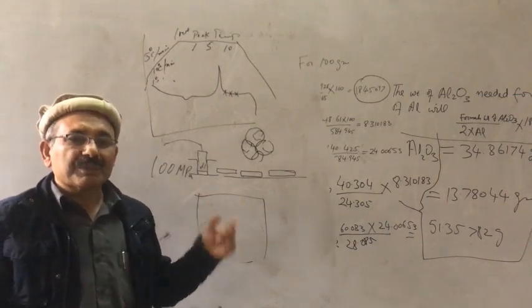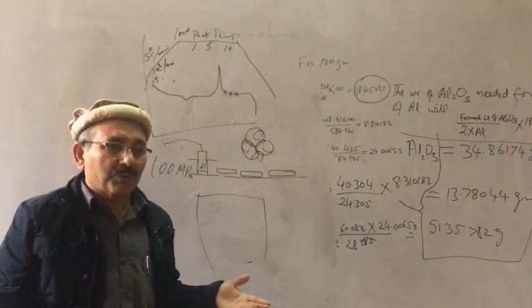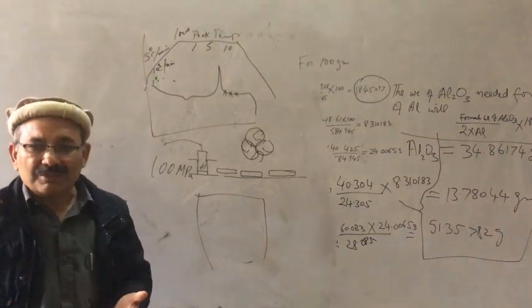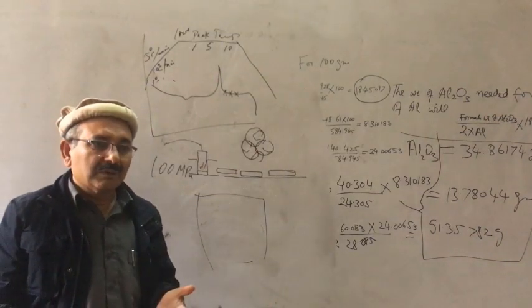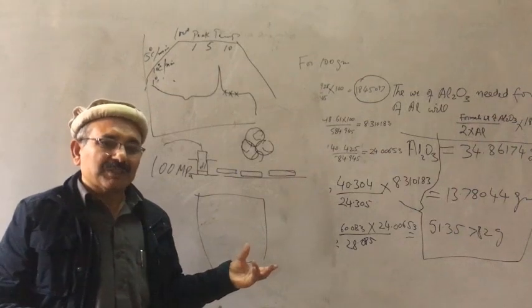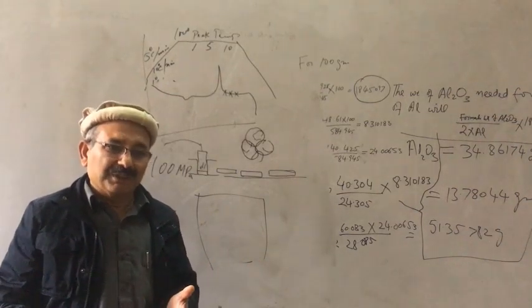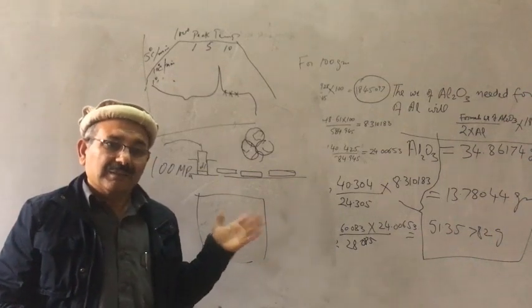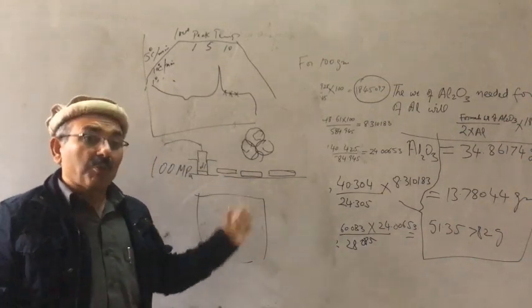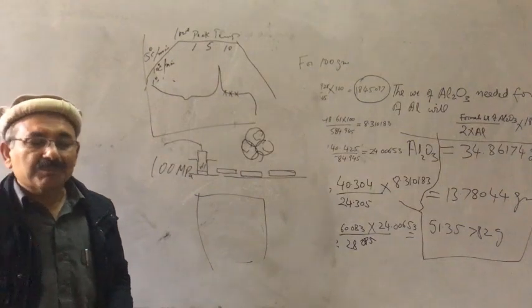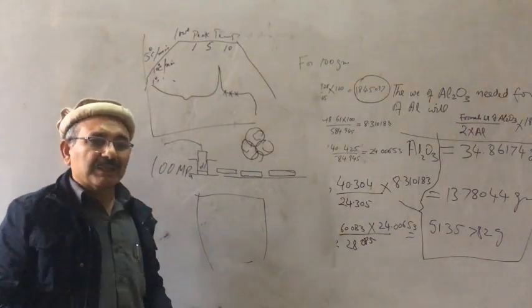But 50% of the material is voids and pores. The dielectric constant of air is 1. So the property you are expecting to be 5000 will be 2500, because you are measuring the property of the pore. That is why for electrical applications people prefer to densify the material.